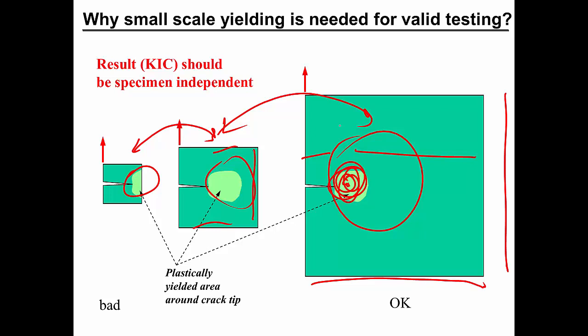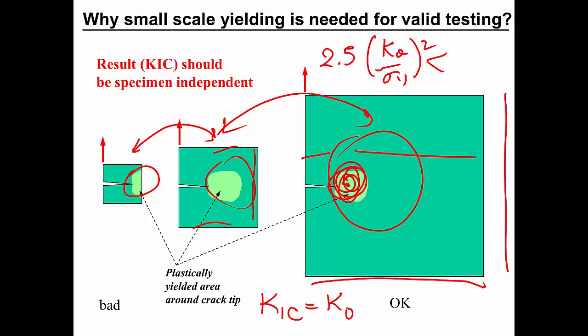This is satisfied when that formula, 2.5 times KQ over sigma y square, is smaller than all these dimensions. So that's exactly the set of conditions, and if everything is satisfied, then we have a valid measurement for the fracture toughness, and what we calculated is exactly the value of the plane strain fracture toughness of the material. If it's not, well, you need to test again.